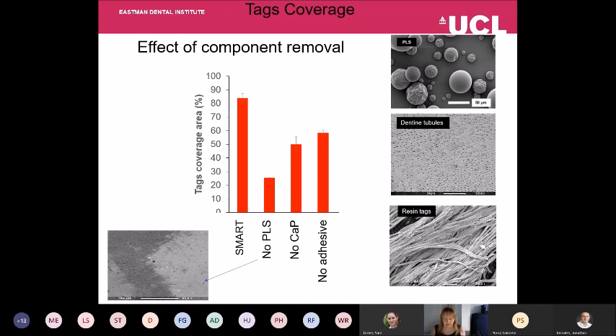If we look at polylysine particles, they're about 50 micron in size. They're far too big to penetrate down into the dentine tubules, which is why we believe what they're doing is drawing out the water from the tubules to allow the resin to penetrate. The calcium phosphate and the adhesive monomer do have some benefit, but the benefit is less than the benefit of the polylysine.